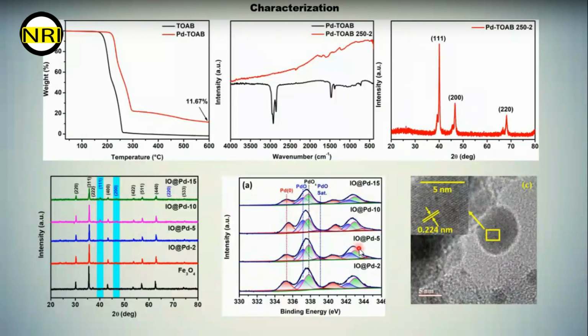And then we took high resolution transmission electron microscopy images, and there also we confirmed that palladium is present, because the lattice fringe of 0.224 nanometer is due to palladium only.